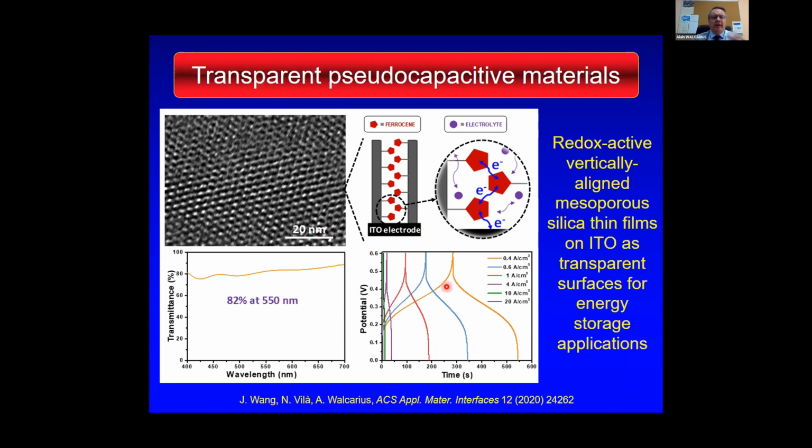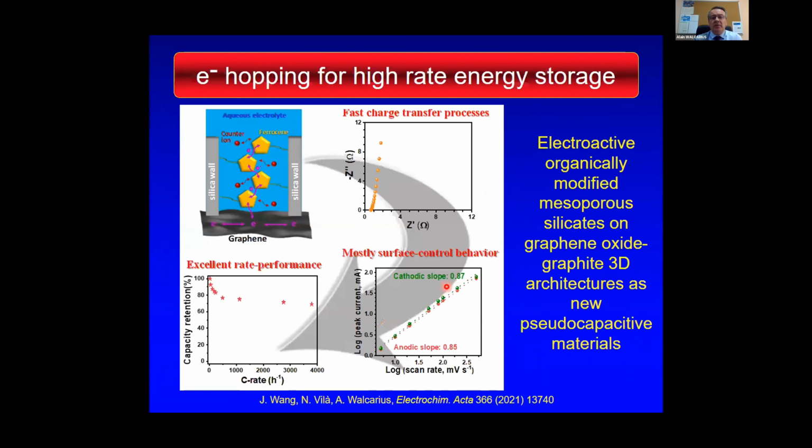But for improving the capacity of these materials, we can also electrodeposit these kinds of films in the porosity of highly porous films made, for instance, of graphene oxide. The graphene oxide can be obtained by the exfoliation of graphite electrodes, for instance. And as this deposition method is applied only on the conductive part of the electrode, it can be deposited quite uniformly in the porous structure of the graphene oxide.